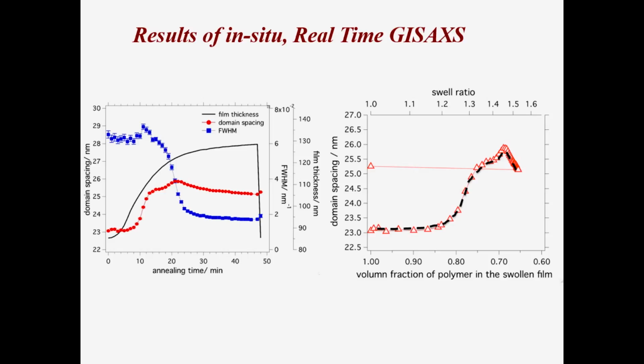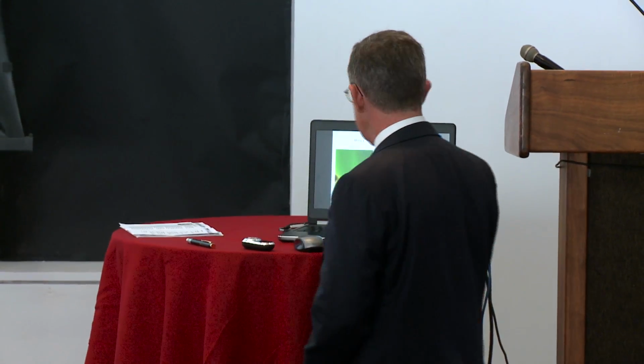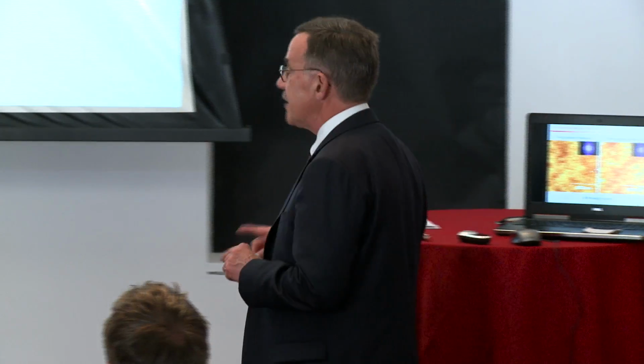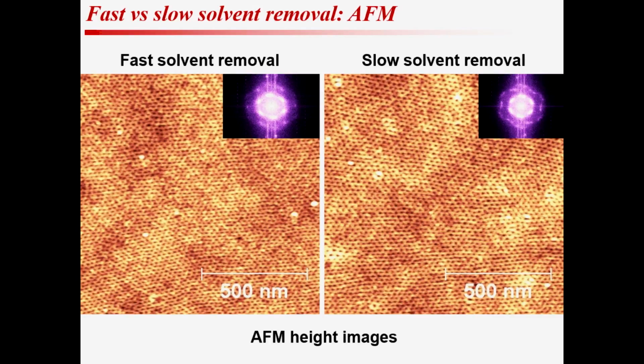And how I get the solvent out is very important because I have several options. One, I could take it out really fast. And if I take it out really fast, that's bad English. Really rapidly. It's an adverb. So if I take it out very rapidly, I can freeze in the structure that I have in the swollen state. Or I can try and ease the solvent out of the film to allow the film to stay in equilibrium and do it slowly. And it makes a big difference because if I take it out fast, the lateral order in the film is much better than if I take it out slowly.